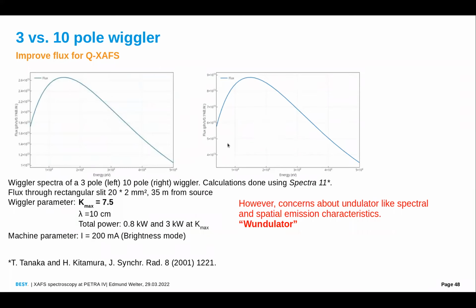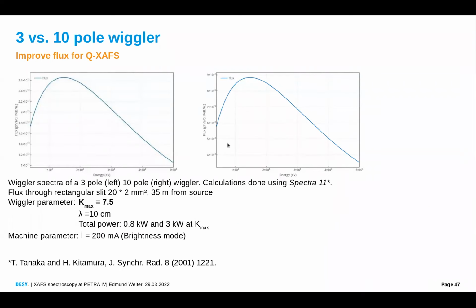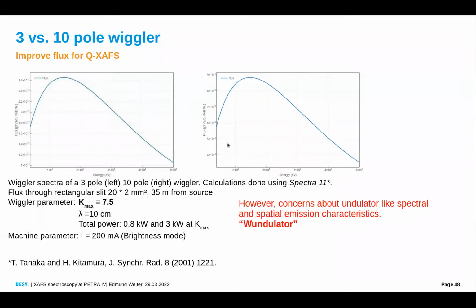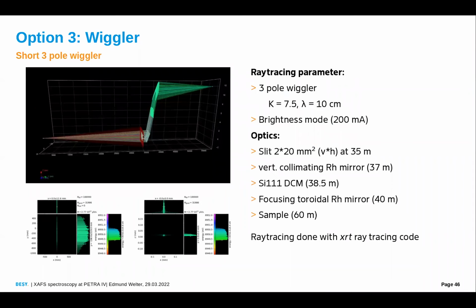If this is usable or not really depends on where we can place our first optical element. I did these calculations here with a slit at 35 meters away from the source. If we could move this to like 20 meters or so, it would be ideal. But here at 35 meters, with the collimating mirror at 37 meters, it requires a mirror with an optical surface longer than 1 meter, and that might already be problematic. I mean, you can use a shorter mirror, but then you lose flux, and there's not much left to lose.